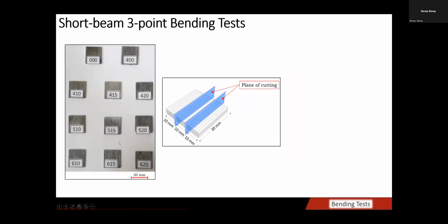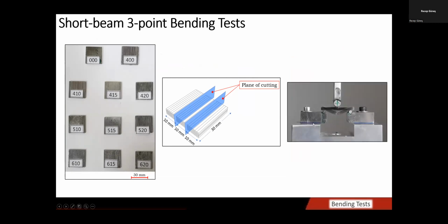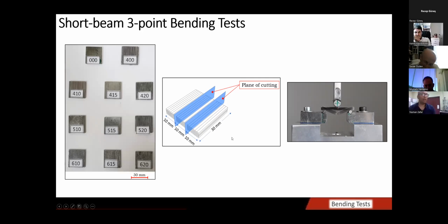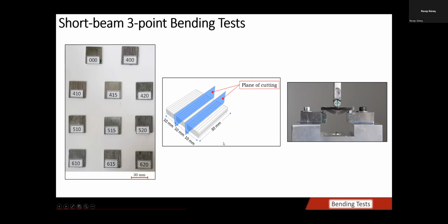The short beam tests of the wire reinforced composites are given here. They are cut from these two planes and then subjected to short beam shear tests. This setup is also domestically made in our lab, and it allows us to adjust the gauge length, the spanning length of the material in the testing setup.